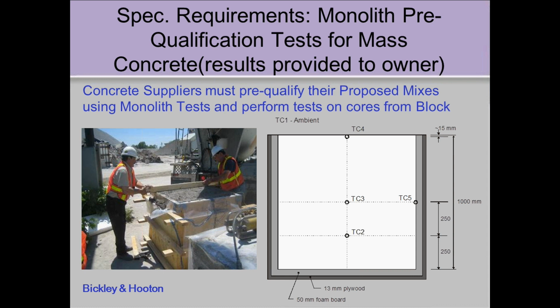One of the things we wrote into this performance spec, and a number of jobs have used this concept, is that we require the contractor to work with the supplier to develop mixes, and we require them to use a monolith test, which in our case suggested a cubic meter of concrete with insulated forms. Instead of casting cylinders and doing the trial mixes with 6 by 12 or 4 by 8 cylinders, they cast a cubic meter of concrete with thermocouples in it, and they look at maximum temperatures and differential temperatures in the insulated mass, and then they take cores. Their tests are all done on cores taken from that structure, not on things stored in a 28-day moist room.